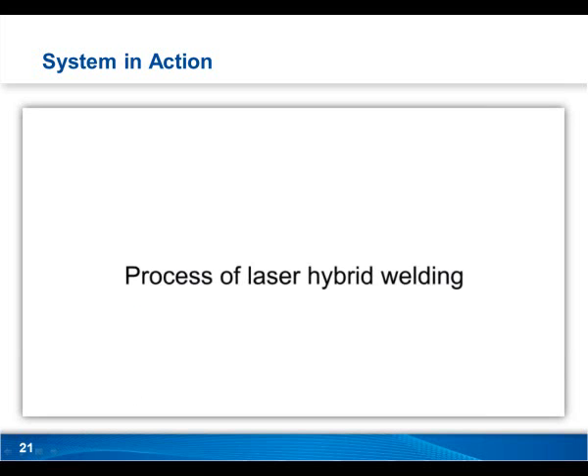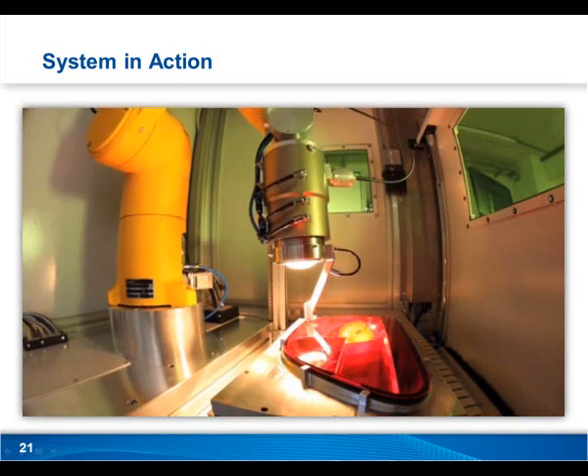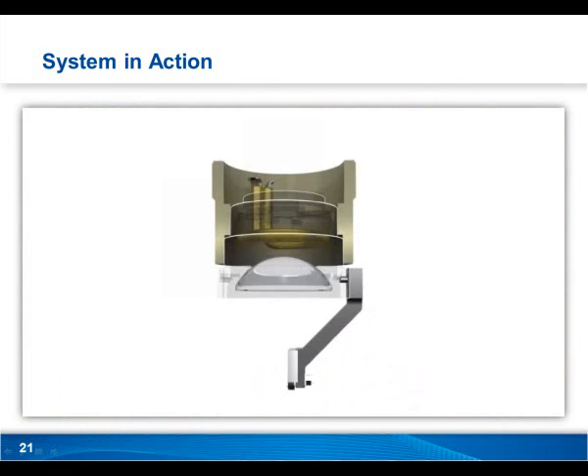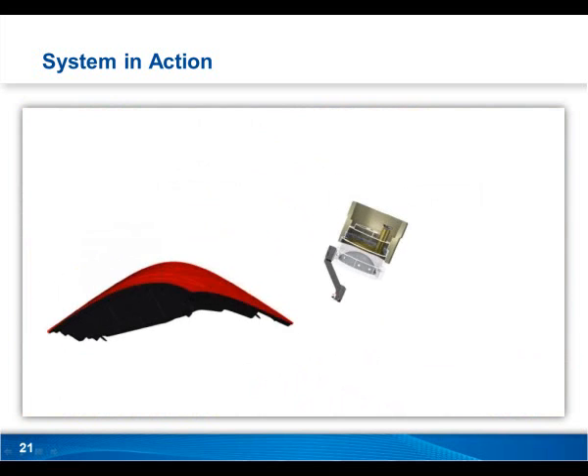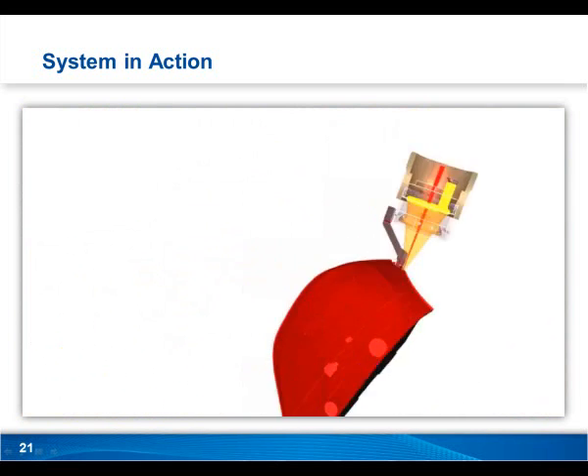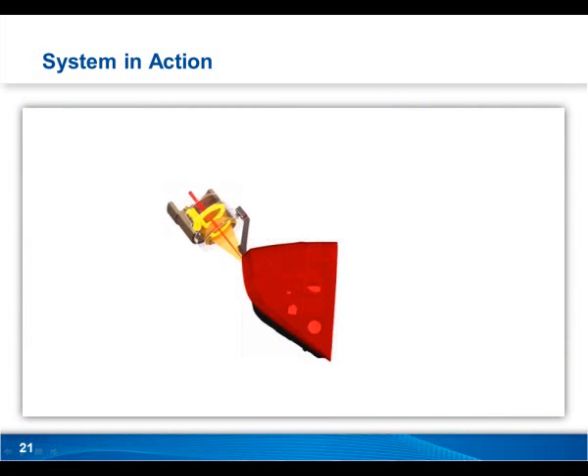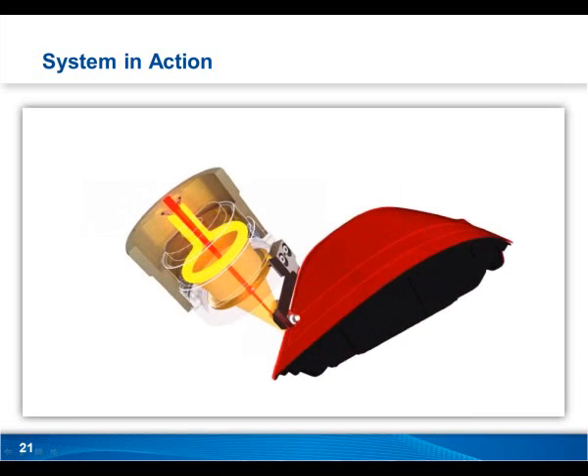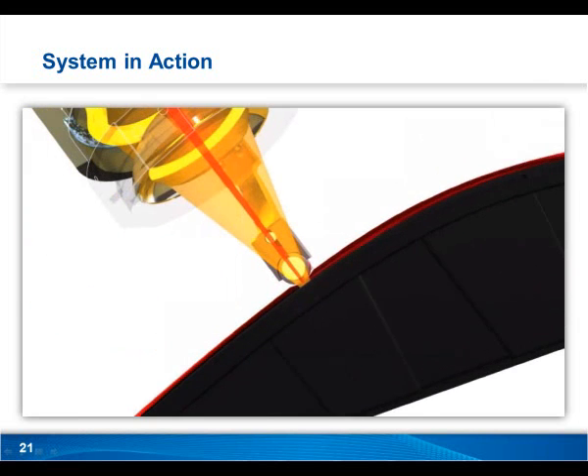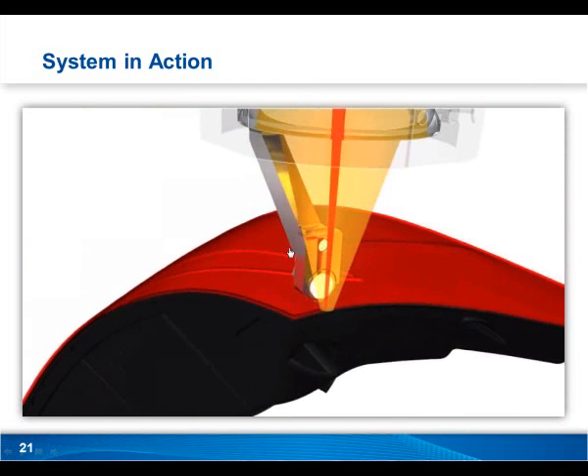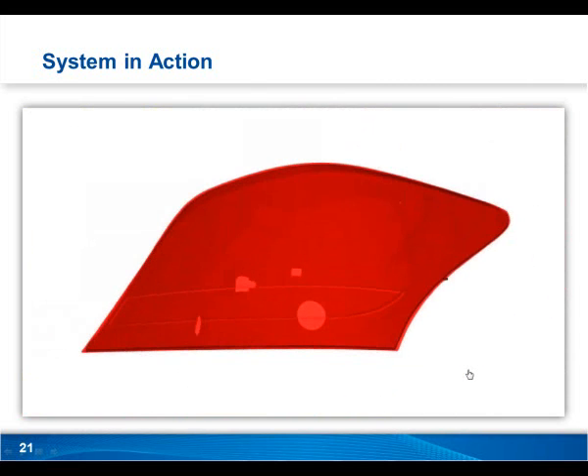So let me show you, this will also help kind of wrap your head around seeing the system in action. Launch that video really quickly. All right, so this is the process of laser welding with the robotic assisted halogen source. You'll get to see the cross section here in action. So see, the halogen light will light up, and that's essentially preheating the plastic. It's a larger heat affected zone than what you get with just the laser. Where the polychromatic light is volumetrically heating the upper part. So you can see the slightly larger heat affected zone than the laser. The roller arm here, that's where we're applying the clamping. And then you get a nice, clean, consistent weld.